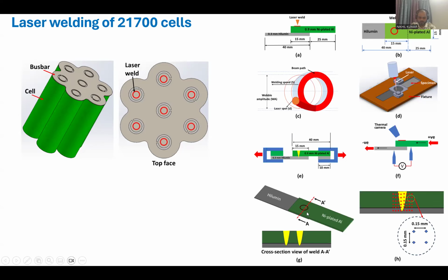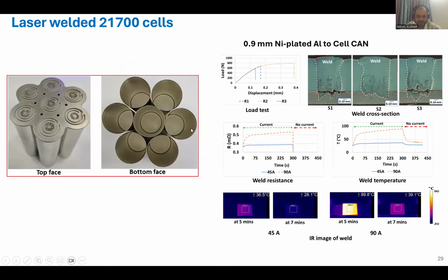And this is the weld cross-section analysis, where you check whether you are penetrating the bottom sheet 100%. The hardness analysis is an additional test I did here, because these are two dissimilar materials: nickel-plated aluminum and the steel can, two different grades with different thermal and electrical properties. Finally, by following those steps, doing the coupon-based trial, resistance, temperature and lap shear tests, I optimized the parameters successfully.